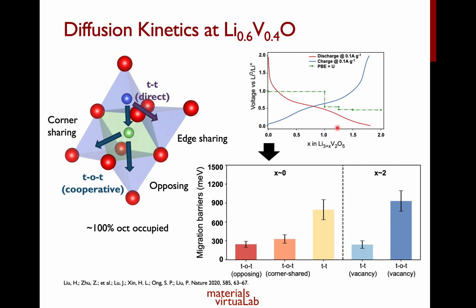What we found was that at least at x equals 0, which is Li3V2O5, that cooperative process in which you have two lithium moving together has much lower diffusion barriers than the direct tetrahedral to tetrahedral hop. The barriers for all the cooperative mechanisms are about 300 meV or below, while for the direct tetrahedral hop, the migration barriers for lithium are close to 800 to 900. So basically, we found that you do have a very fast diffusion pathway at the Li3V2O5 composition.